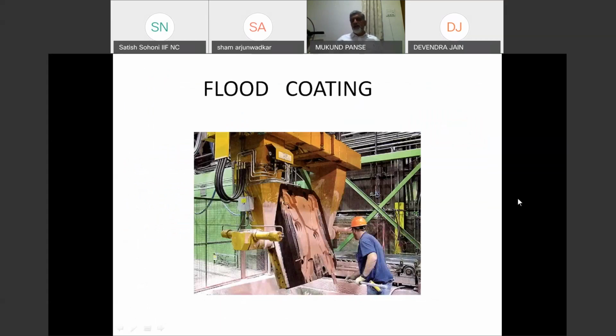The last process is flooding. In flooding, actually a normal garden hose without any pressure or a normal hydraulic pump pressure is used. It is used for very heavy and odd molds. You have to have a mechanical arrangement to hold the mold tilted, and also a mechanical arrangement to collect the paint which drops in the tank, filter it and reuse it. It is basically suitable mainly for water-based paints on no-bake large molds. It can also be used for cores, but it is better that the cores are on a turntable, so they move continuously, so the coating gets spread properly, and there are no runs and drippings.